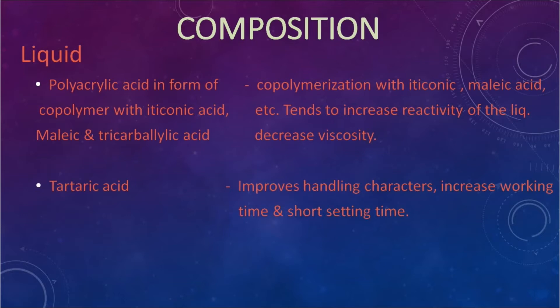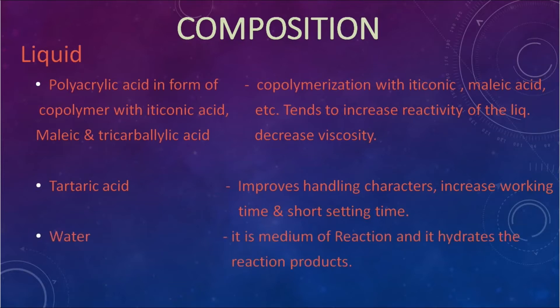Co-polymerization tends to increase reactivity of the liquid and decrease viscosity. Tartaric acid improves handling characteristics, increases working time, and decreases setting time. Water serves as the medium of reaction and hydrates the reaction products.